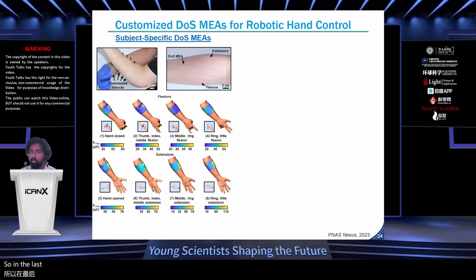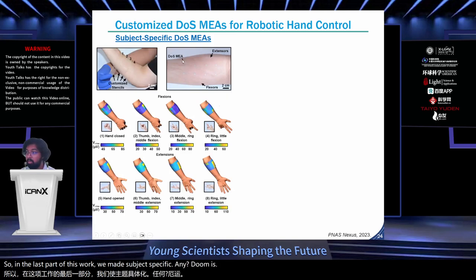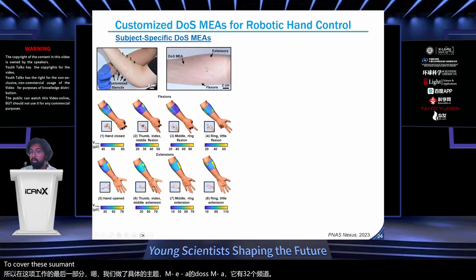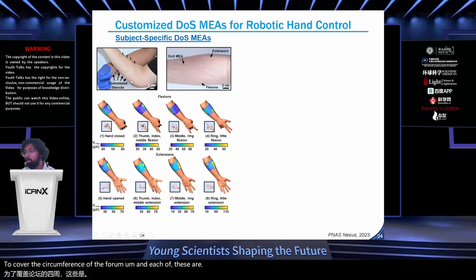So in the last part of this work, we made subject-specific DOS MEAs, which had 32 channels to cover the circumference of the forearm, with different stencils to match the circumference for each particular subject. We compared the EMG data while recording for various different gestures, which are shown on the last slide, adding the opposite of the flexion extension here. And we compared this data to that of two FPC grids, so 64 channel grids, so 128 channel, covering roughly the same area around the circumference of the forearm.